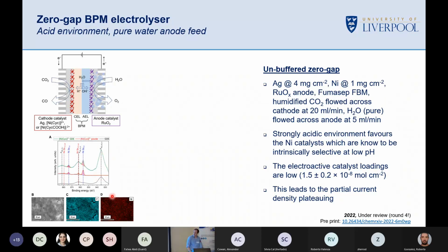Not sure how well people can see this. There is nickel present. We deposit at 1 milligram per square centimetre for the nickel, and we've actually compared that to a silver electrode at 4 milligrams per square centimetre, because we found if we did the silver at any lower, we just got such terrible current density, so we made it harder for ourselves.